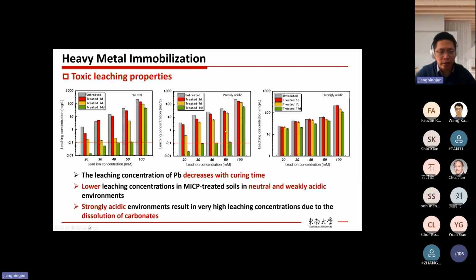And for weakly acidic condition, also, except for the 100 millimole case, for the rest of the cases, 14 days are sufficient to meet the leaching standard. But unfortunately, for the strongly acidic condition, we can see the leaching concentration is very high. It's all more than 10 milligram per liter, far more than the 0.1 milligram per liter standard. And as I explained, because MICP could not work very well under acidic condition, the precipitation could be dissolved. So it means that if we want to use MICP for heavy metal immobilization, we need to be careful about the acid condition we could potentially encounter in the field.